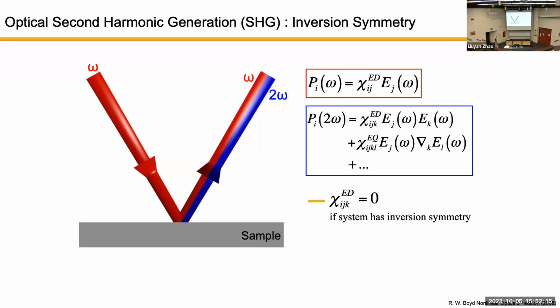The reason for us to do so is because the conventional wisdom tells us that if we focus on the electric dipole process for SHG, it is going to vanish if my material has inversion symmetry. That's why people often tell us that SHG is a great technique to detect inversion symmetry breaking, because the leading order is not going to be there if the inversion is there, and will show up if inversion is gone. Okay, but there's a caveat.